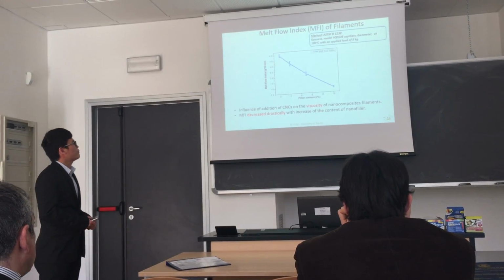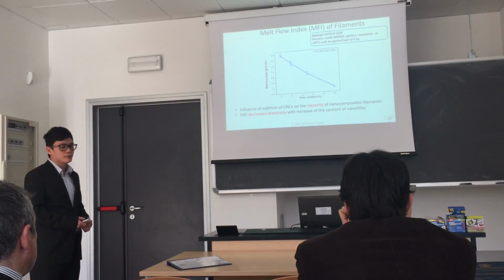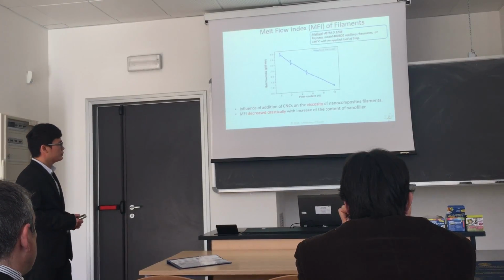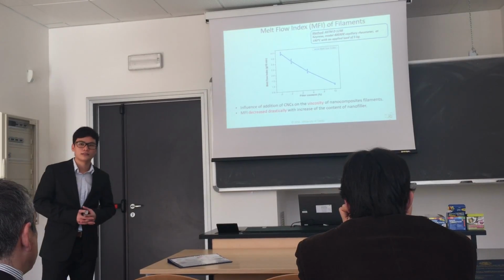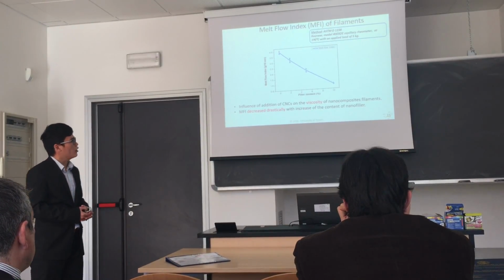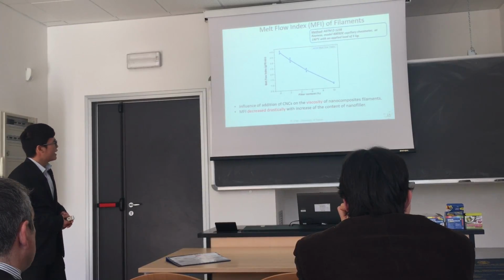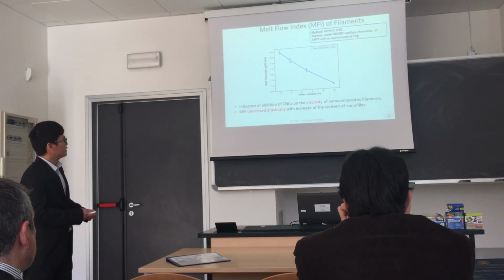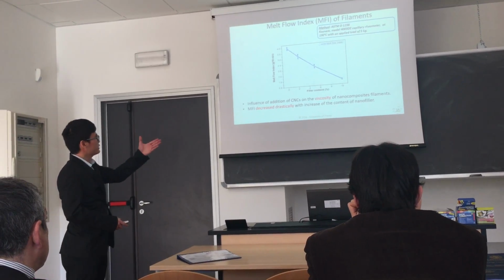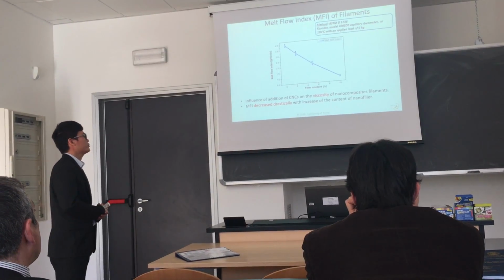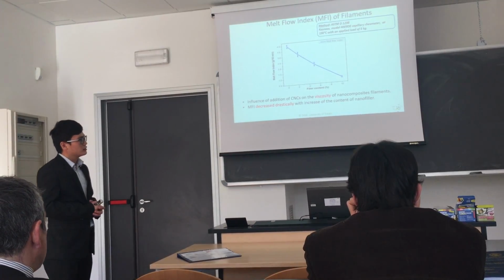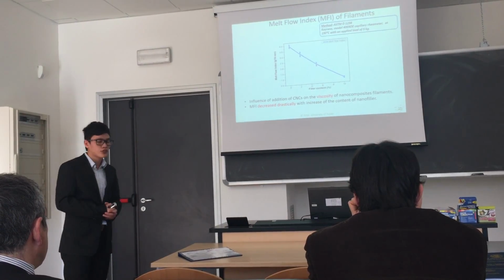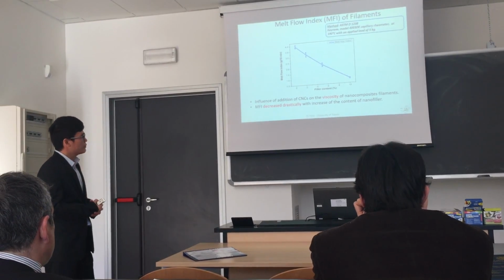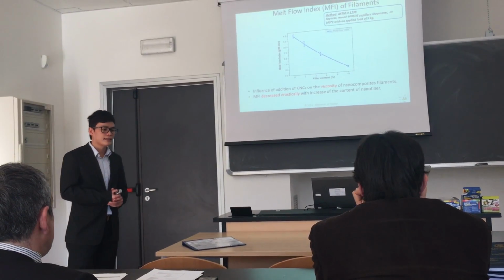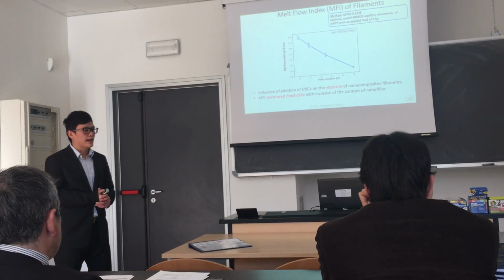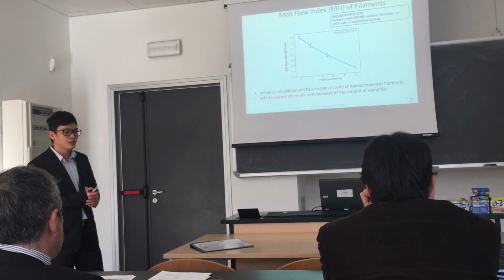Let's move to the melt flow index test, MFI, of the filaments. This test helps us to assess the influence of the nanofillers on the viscosity of the nanocomposite filaments. And we can see clearly from the graph that the melt flow index decreased significantly with the increase of the content of the nanofillers. And in these figures, I could not obtain the value of the composition with 20% of nanofillers because this composition is too viscous. And this is one of the reasons that I cannot use this composition for the 3D printing application.